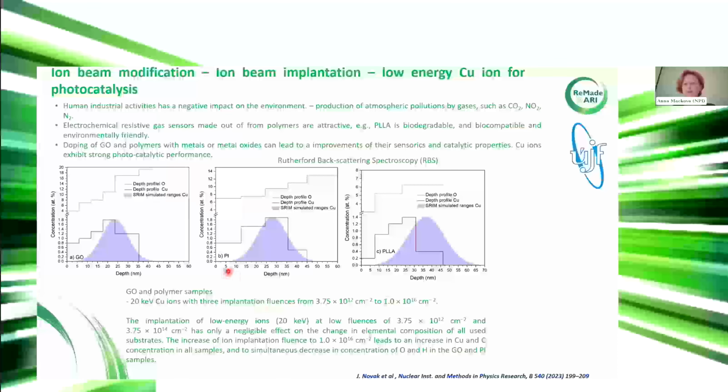And you can see here the simulations again, which must be done before. Rutherford backscattering spectrometry is employed, and we check the chemical composition after the irradiation, where we see very good agreement with the profile of oxygen, depletion of oxygen. And here is the profile of copper. This is experimental, and this is simulation.